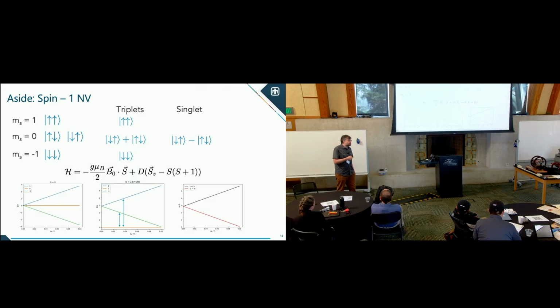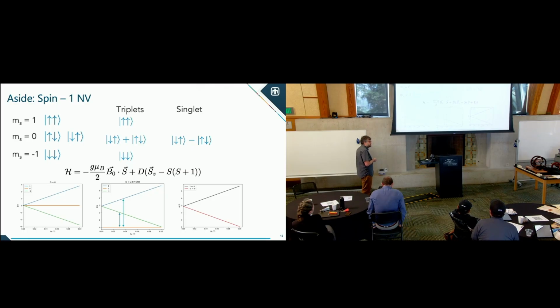Okay. Now you actually have two sets of magnetic resonance, though. If we add a D parameter, which is this dipole interaction, and for the NV it's particularly 2.87 gigahertz. All right, so this is what we call the zero field splitting. That actually increases the energy at zero magnetic field for the plus or minus 1, still degenerate at zero field, to this 2.87 gigahertz. And now you have two transitions, resonances, from -1 to 0 and 0 to +1. So these are two different magnetic resonance transitions that you typically see and can control.